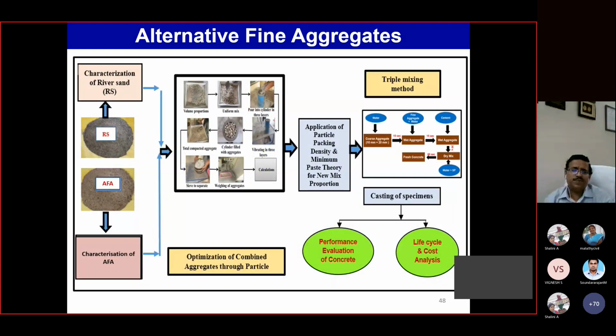We have also optimized that, and developed a minimum paste and maximum density mix proportioning system, so that we can minimize our cement consumption as well. For M30 grade, it normally requires about 380 or 375 kg of cement. If you do it with minimum paste and maximum density, it needs only about 340 to 330 kg. So you have a saving in cement.